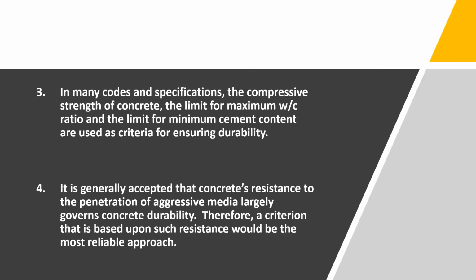Okay. In many codes and specifications, compressive strength of the concrete, the limit for the maximum water cement ratio, and the limit for the minimum cement content are used as criteria for ensuring durability. So it is generally accepted that concrete's resistance to the penetration of aggressive media largely governs the concrete durability. Therefore, a criterion that is based upon such resistance would be the most reliable approach. That means instead of prescriptive parameters, we have to go for performance-based parameters.